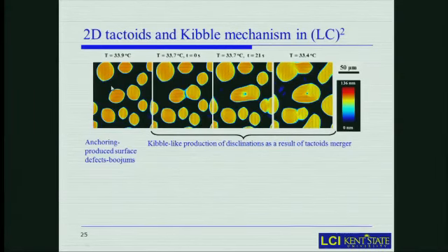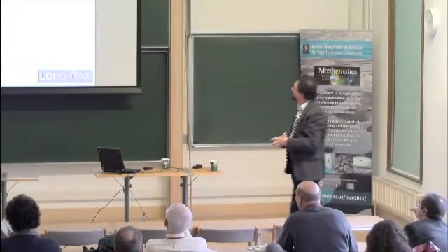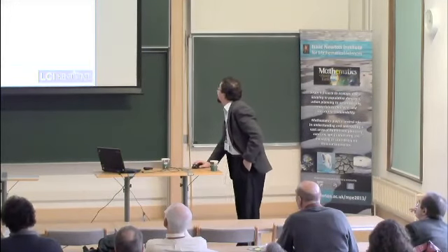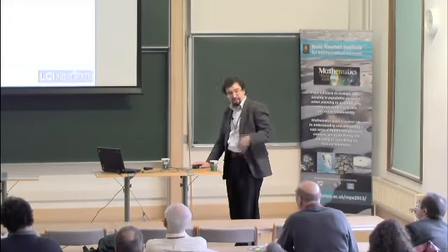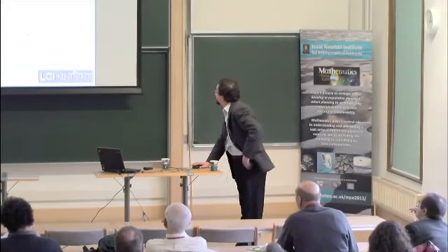So here's the bigger sample. What you see is the appearance of the nematic germs, nematic nuclei, and then they start to coalesce. And what is shown here is the result of two domains coalescing and forming a topological defect, a disclination of strength -1/2, right in the center. And so it's indeed very similar to the Kibble mechanism.